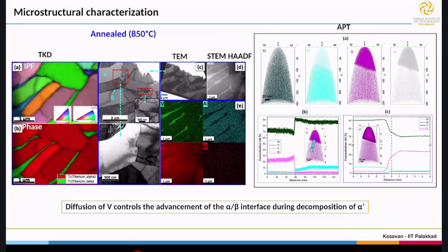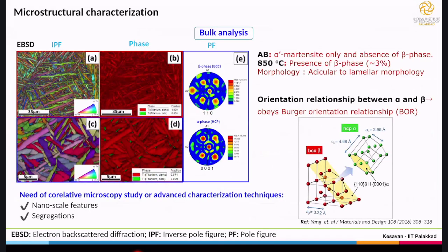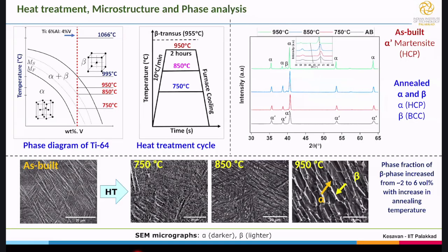See, again, the resulting structure depends on the cooling rate. I think I have shown it, sorry, I'm rushing my slides. Yes, see here, this is the beta transition temperature. If I take it above the beta transition temperature, of course, the size of the laths or grains will become extremely large, and the grain coarsening effect will come into the picture, and that will lead to other issues. There is a sudden drop in ductility and strength as well.